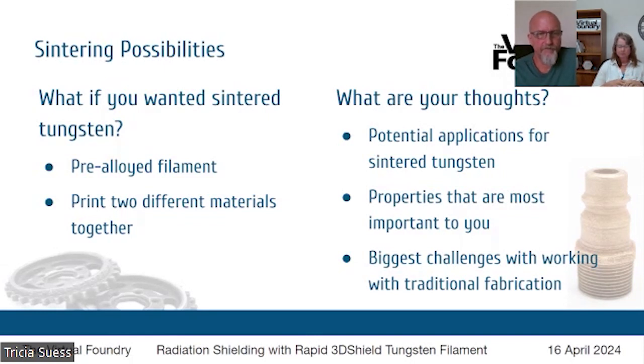Yeah, we're working on a few versions of this. Some of them will be like a tungsten boron pre-alloy or something like that. The other option is liquid phase sintering, where you'll use exactly the same tungsten, but you infuse it with a material that melts at a lower melting point. I've done this in experiments with bronze, so we wind up with essentially tungsten particles bound together by bronze. So there are options here, though most of them, well, all of them at this point would require some development. In time, the Virtual Foundry will release a sinterable version of some type of a tungsten alloy.